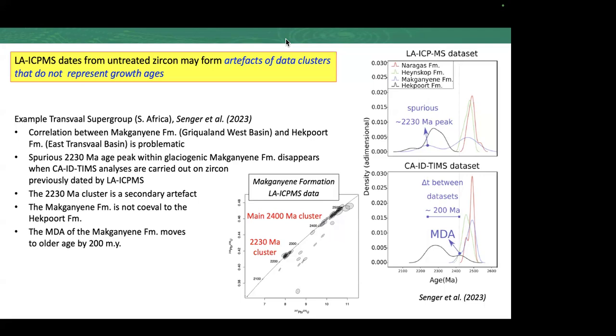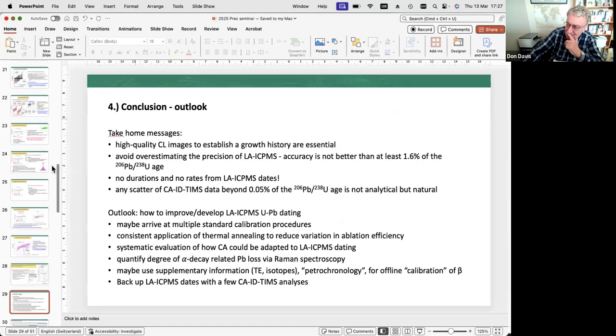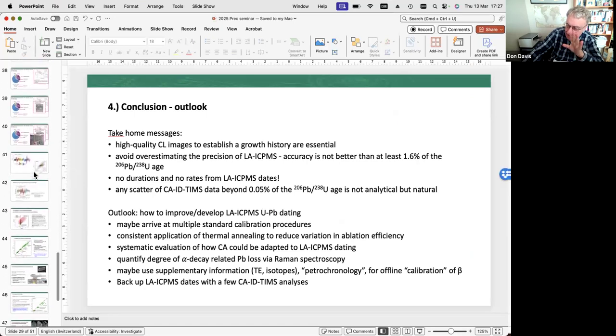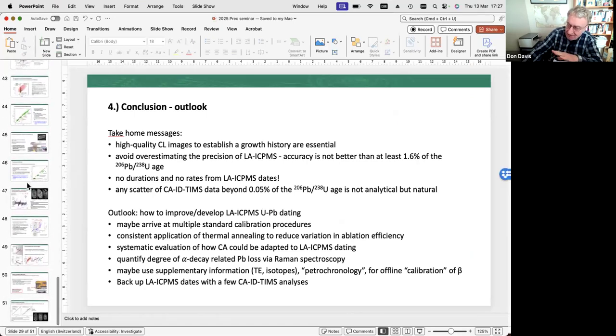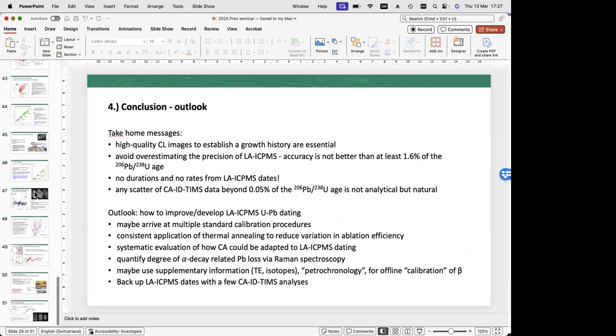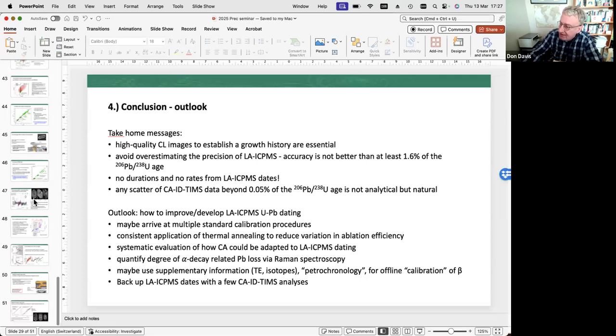So it is tricky. I agree that we need to move in that direction, but I don't know the solution, because the chemical abrasion just changes the lattice too much, and then the laser doesn't work the same way it does in the standard, and you've introduced a problem then, especially for Phanerozoic, as you pointed out. You disturb the uranium lead ratio, you're toast as far as getting a good Phanerozoic date. Yeah, I pointed out before, if you try this on zoned zircons, the chemical abrasion, you can get a reverse discordance because of alpha recoil from the high uranium zones, which are dissolved out into the low uranium zones. So your age may be a bit too young, the 7-6 age.